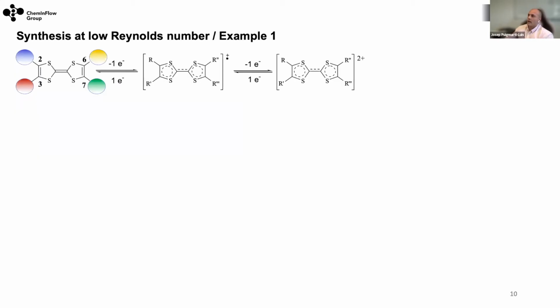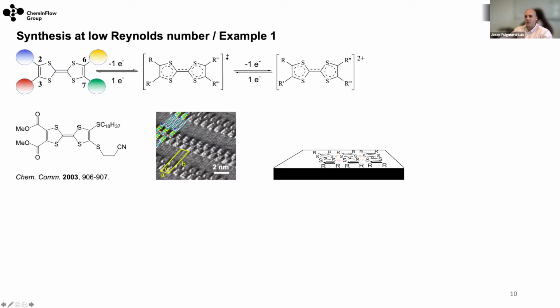So, during my PhD, I was working with this molecule here, tetrathiafulvalene, TTF. I'm an organic chemist, by the way. So what I used to do was to derivatize the TTF with different functional groups in these positions, because as you know, the TTF is very well known in the field of molecular electronics. So what you want is an organization where you have a very good pi-pi stacking of this molecule, so that when you oxidize or partially oxidize the structure, you will achieve the formation of a conductive material. Here I'm just showing some results that were developed in the group of Professor David Amabilino. I did the thesis with Professor David Amabilino.